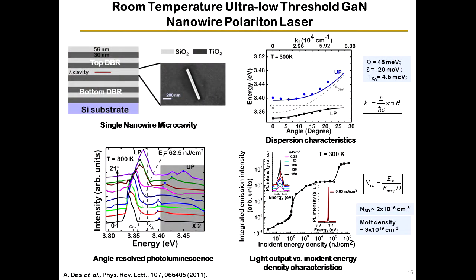But everything was at very low temperature because they were using gallium arsenide microcavities, and as I showed you in the beginning, gallium arsenide has an exciton binding energy of 5 meV, and so you could not use it at room temperature. So they were all at cryogenic temperatures. So here the first thing we did was take a single nanowire, disperse it, separate it out, identify a single nanowire, bury it in a microcavity, and there you are.